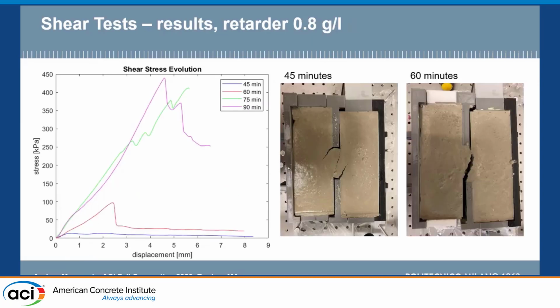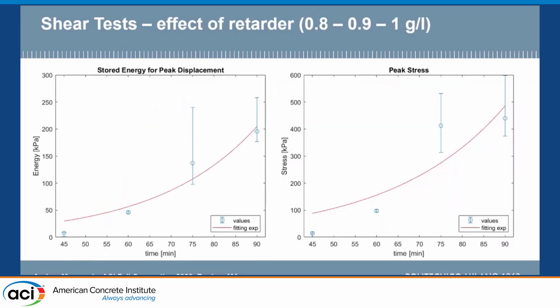So these are the results for the retarder at 0.8 gram per liter, and as you can see, there is a clear distance between the 75 and 90 minutes curves compared to the first two. In fact, there is almost a phase transition, so that at 75 minutes the material is almost solid, whereas at 45 minutes it is plastic, as you can see here from the picture, but with limited strength that starts developing only at 60 minutes, where the material is still in its plastic stage. As you can see, there is an exponential increase of the strength between 60 and 75 minutes.